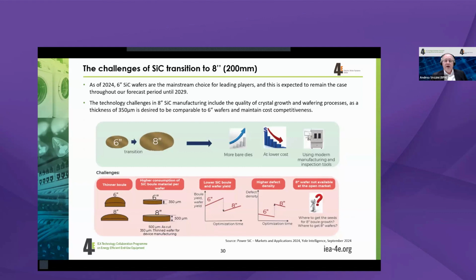So there are some companies who have completely switched to 8-inch. Wolfspeed is one of these companies, and they have faced, on the other hand, also some challenges. The challenges are that when you grow silicon carbide on an 8-inch wafer, you will have a thinner boule, basically less output, which additionally, when you're cutting it, makes it very difficult to cut it to the same slice thickness as in a 6-inch application. So again, the yield of this boule is even decreasing. Apparently, this has been solved now, and they're closer to 350 than they've been to 500.